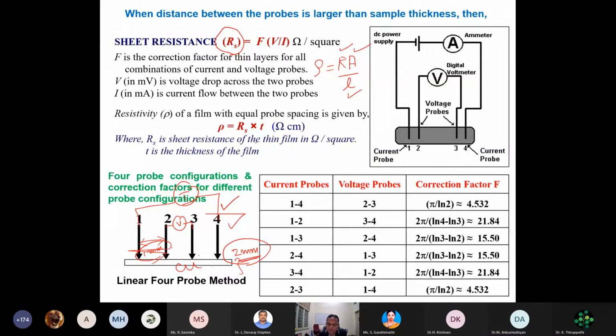Whereas in the case of thin films, we are dealing with a very, very thin film. The film will be of the order of say 100 nanometer. 1 nanometer is 10 power minus 9 meter. Whereas the probe spacing which you are keeping to measure the resistance will be 1 millimeter. So 1 millimeter is much, much, much larger compared to 100 nanometer. In this case, the standard formula for measuring the sheet resistance or the resistivity will not be valid, because the current path taken in this particular case will be very different.